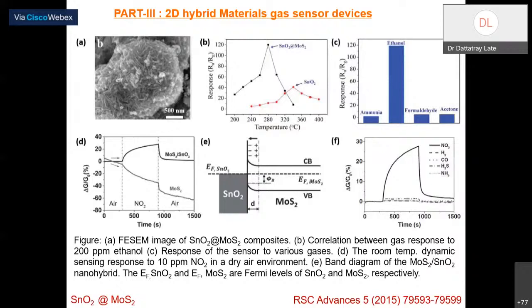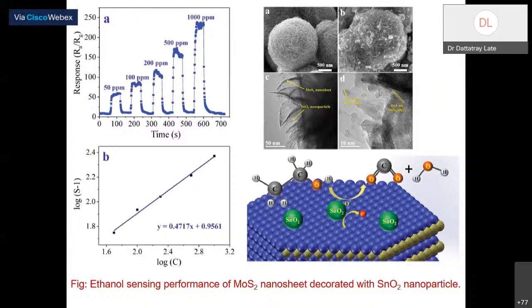And actually, you can design the band structure of the material depending upon the thickness of your MoS2 and the size of the nanoparticle, the traditional nanoparticle like SnO2, zinc oxide, and all these things. So this gives you better sensitivity and selectivity for these traditional materials. For example, you can see here the response of these hybrid materials, and these are characterization techniques. For example, this is a TEM image of these hybrid materials, and you can see exactly in the right corner how MoS2 is coated on SnO2, and these are well separated SnO2 nanoparticles on the MoS2 surface.